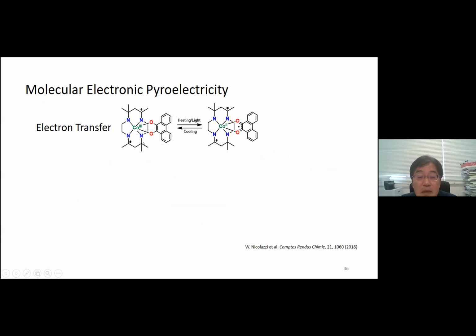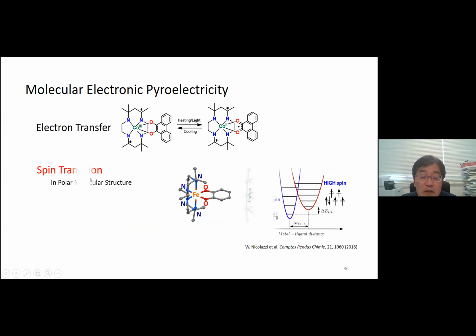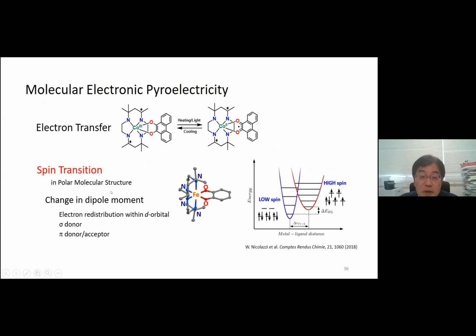Now I talked about polarization switching using electron transfer. But as you know, there are many more dynamic electronic processes, and they can be used as a source of polarization switching. And in this study, we investigate polarization switching using spin transition in a polar molecular structure. And spin transition is accompanied by electron redistribution within the orbitals and also between metal and ligand. So spin transition in a polar molecular structure should exhibit a dipole moment change, which should be detected as polarization switching. So we investigated the polarization switching behavior of a spin transition compound.